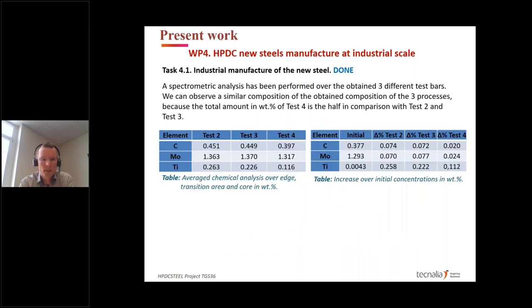What we got finally, we got an understanding that there's an increase of the carbon concentration in between test two, three, and four in comparison to the initial composition. So the initial composition has been 0.38% of carbon, 1.3% of molybdenum, and 0.004% of titanium. And following tests, actually, we got an increase of the carbon concentration, of the molybdenum concentration, and the titanium content.